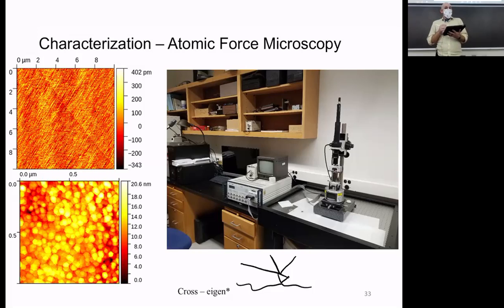When we're working with materials that are not ideal, like indium nitride, the shape of the material starts to mess with the way that the tip interacts with the surface. So if you're dealing with a tip that has a broad shape like this, and you can't get into the gaps between your materials like this, you can't see the material. You have to make sure that you have a tip that is sharp. And that way you can get in between each of these gaps. Now, that sounds simple, and it sounds like, yeah, of course you should know that. But when you're in the middle of research and you buy a $100 pack of tips and they're not working, you kind of forget some of the reasons. And you feel really stupid when you realize your tip wasn't shaped correctly. Lessons for the future.